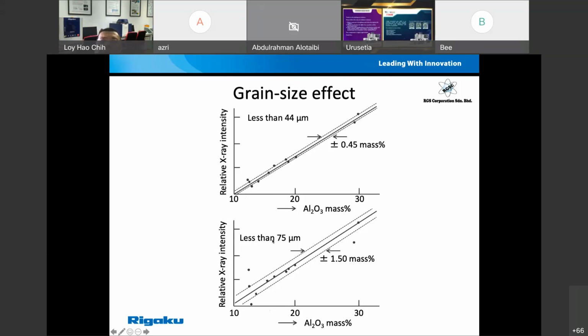Compared to that, if your grain size is much larger, as large as 75 microns and above, maybe sometimes even 100 microns and above, then you can see that for the same sample the fluctuation range will be much bigger compared to a much finer grain size. This is why we always recommend that you grind your samples to less than 50 microns. Once you do that, you should follow it for your future samples. Don't grind at 75 microns today, then 45 microns tomorrow, because that will give you errors in measurements.